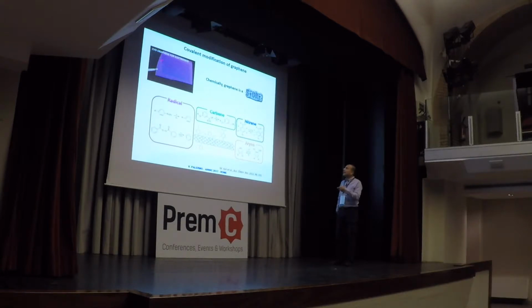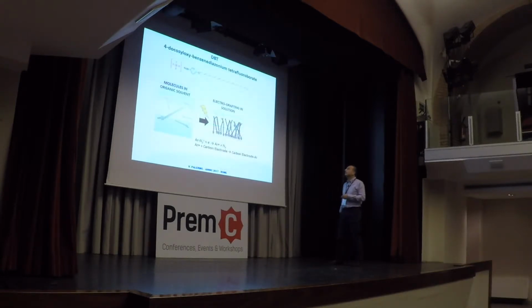What we did was to enhance its reactivity with electrochemistry. So we use this molecule. This is a diazonium salt. So upon the right stimulus, it loses nitrogen, creating an aryl radical. This can react with graphene, but takes some time. The approach is instead to dip graphene or graphite in a solution of these molecules. Then you apply an electrochemical pulse, and this makes the surface more reactive, so you have a charge transfer between your molecule and the electrode, and then this creates a radical that targets and sticks to graphene very quickly.